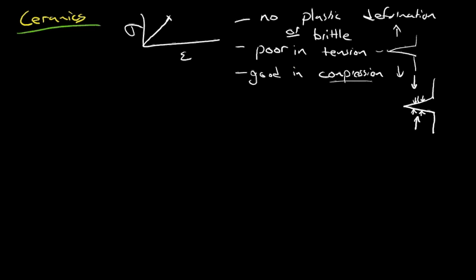So why is this? What's going on? And can we quantify this? Well, so the first thing to appreciate about ceramics is a lot of ceramics, because they have strong bonds in them, they've got strong bonds, high bond energy. They're typically ionic, although you can also have covalent ceramics. In either case though, the bond energy is usually pretty high. And so that also translates to a high melting temperature.